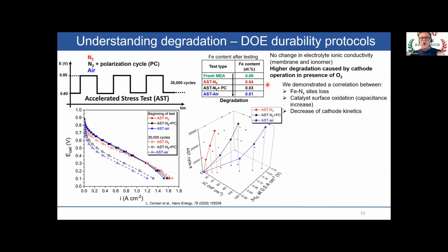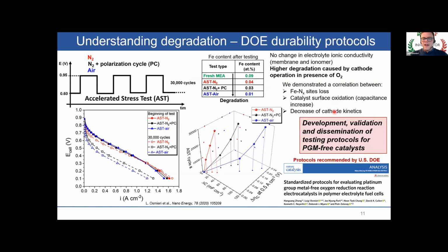And this degradation correlates well with the loss of iron sites, the oxidation of the catalyst surface, and the decrease of the cathode kinetics. So these findings were then used later for developing, validating, and disseminating the testing protocols that are now recommended by the US Department of Energy for testing and assessing performance and durability of PGM-free catalysts for PEM fuel cells.